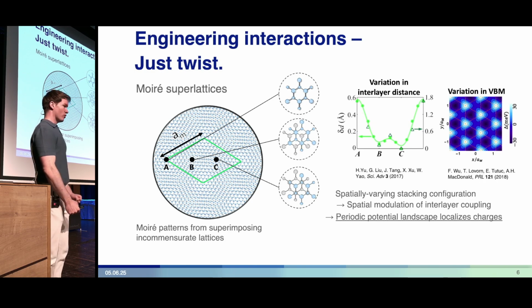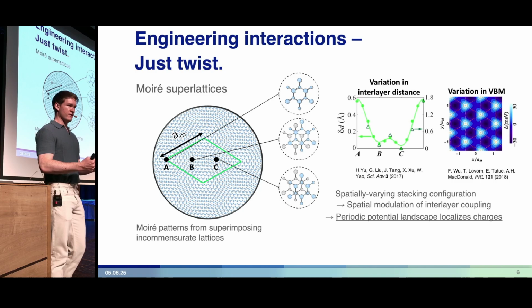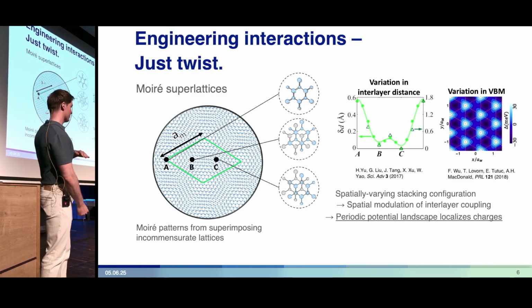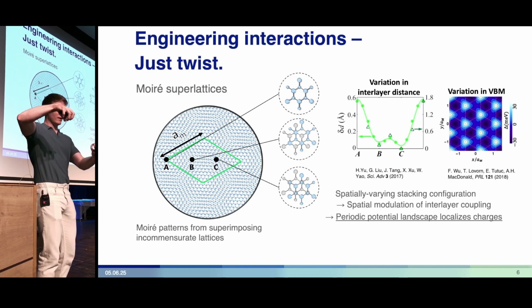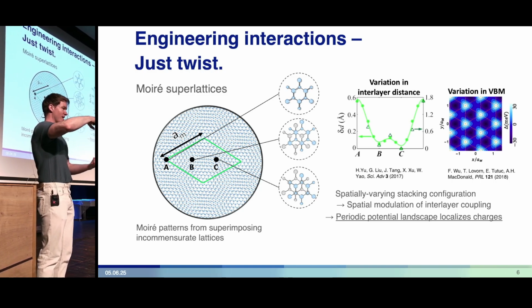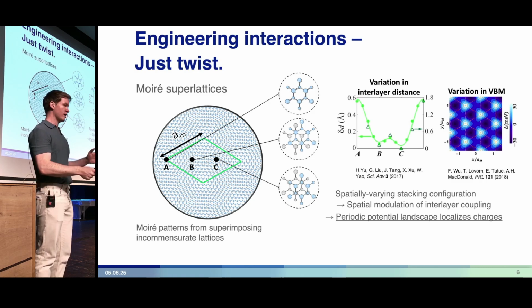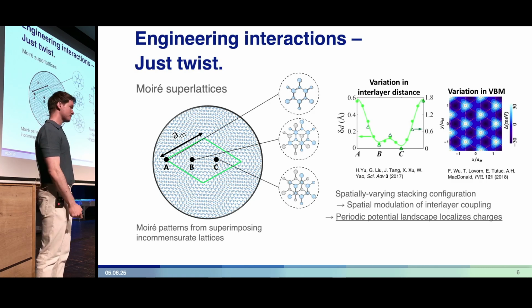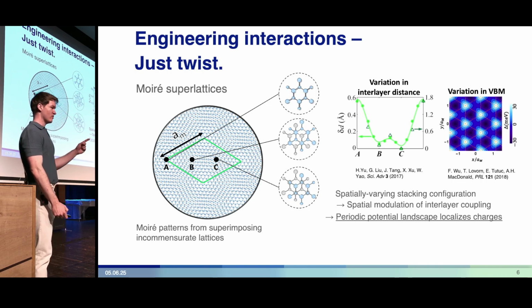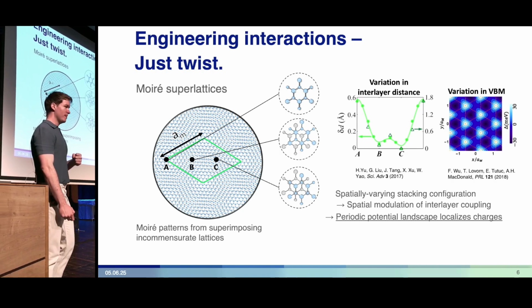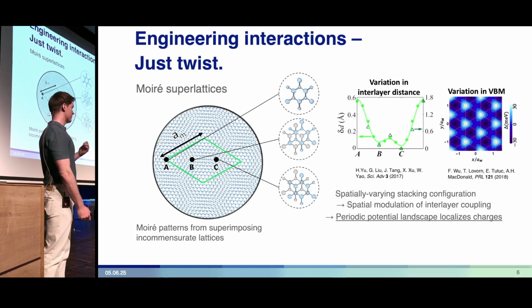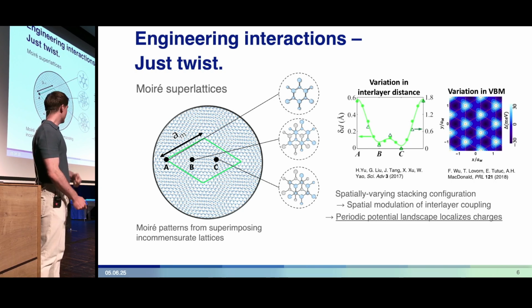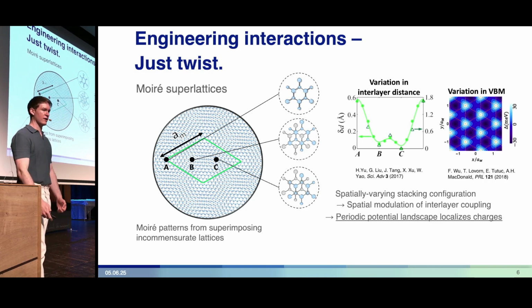And this has some really important consequences for the electrons that live in the Moiré. First of all, as I move across the Moiré unit cell and the atoms line up with each other differently, the layer separation will be different, and the overlap between different orbitals will change from point to point. This means that tunneling between layers at different points in the Moiré unit cell is modulated, and this actually introduces a modulation into the conduction and valence band edges, resulting in an effective, lattice-shaped potential, which can localize charges either in the conduction or valence bands.